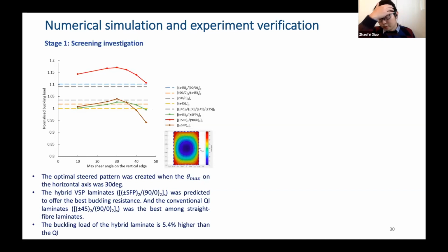So if we look at the results of the numerical simulation, we found that when theta max reaches 30 degrees, we achieve the optimum steered pattern, and we found the hybrid laminate, the SFP 90, offers the best buckling resistance, and the conventional QI laminate was the best among the straight fiber laminates. And the improvement ratio of the hybrid laminate is 5.4% compared to the conventional QI.